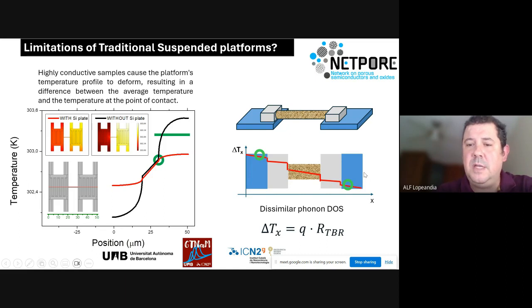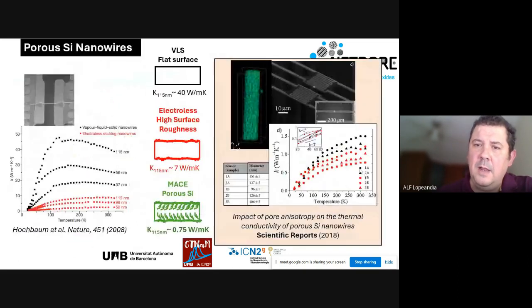And of course, as we have different materials with different phonon densities, we will have a TBR, a thermal boundary resistance, and we will have a temperature drop between the different materials that could be significant. And could be significant means that in previous measurements, we had very low thermal conductive materials. The thermal resistance of these materials was huge.